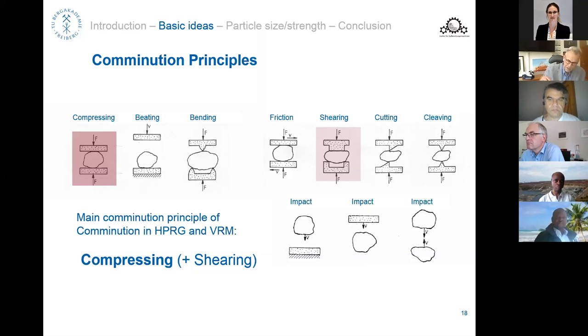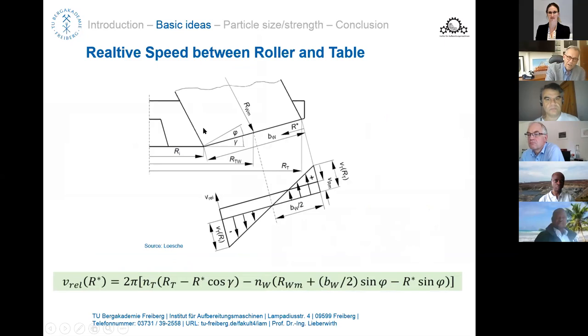And with these marks, we could find underneath this layer and on the surface of the roller, between the studs, even the directions in which the material was flowing. You could see very clearly that in the center of the roller, the material was flowing in the vertical direction, while towards the sides of the roller you could very clearly see indications of the material being squeezed to the sides, and you had a clear wear direction in the sides. So which means you also have a shear load in the material in the HPGR, not as much, of course, as in the VRM.